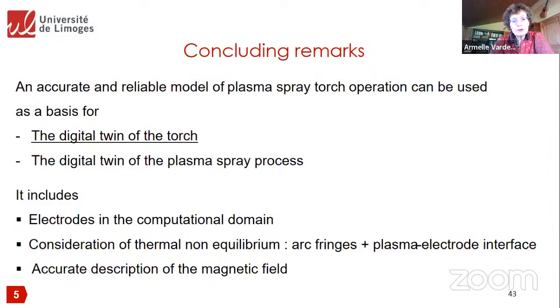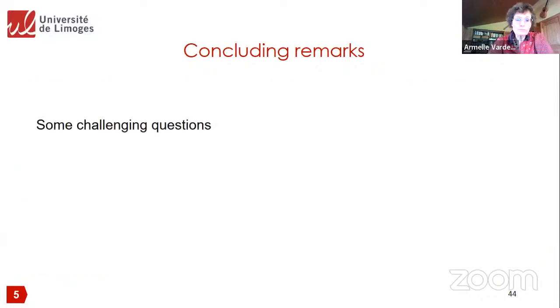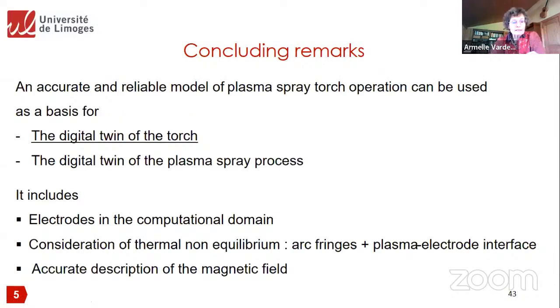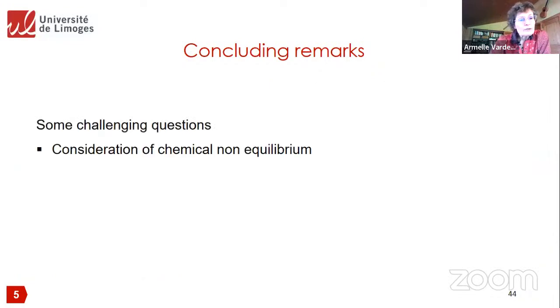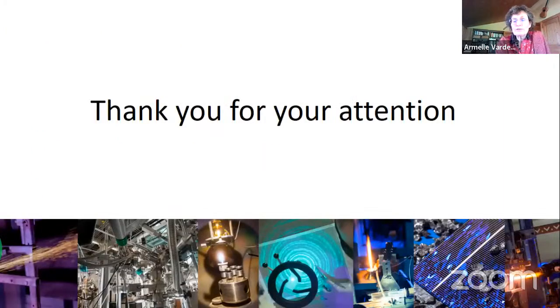It will consider the thermal non-equilibrium in the arc fringe, but also at the interface between the electrode and the plasma. And it also needs a very accurate description of the magnetic field. Okay. I will stop my presentation here, but in fact, there are many other questions about this type of model. For example, we don't take into account the chemical non-equilibrium. And one of the key issues is how we can predict the anode, which is an important point and a weak point in thermal spray. It's how the anode will behave during the process and how this will affect the processing of the materials. Okay. Thank you very much for your attention.